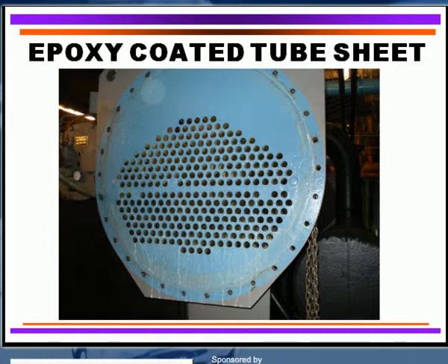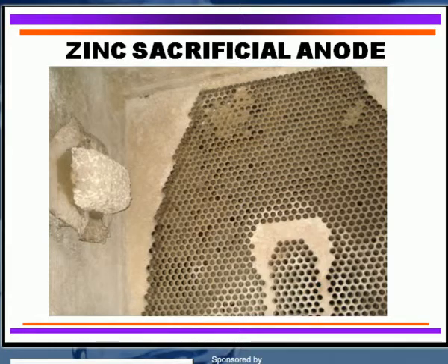Some people have actually used other techniques too, which is still worthwhile, and that's the use of the zinc sacrificial anode. That's an example of that block on the left-hand side. This happens to be in a utility power plant condenser. The zinc sacrificial anode corrodes in preference, protecting the metal surface around it, so it has to be in direct contact with the metal surfaces you want protected. It'll corrode, and the zinc will go back into solution and be carried around with the circulating water. Soluble zinc salts are a corrosion inhibitor for carbon steel, so you get some benefit from that.